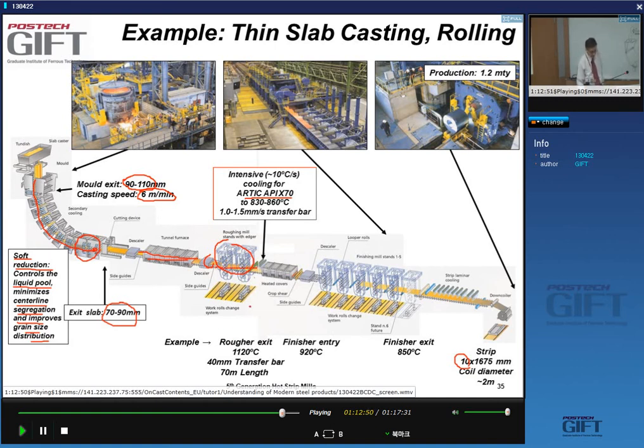Then you go to a tandem rougher. Typical example of what you get at the exit of the rougher is 40 millimeters, so that kind of doubles the length of your transfer bar, about 70 meters. You go through a transfer position where you keep the bar heated, and then you go through the finishing mill.